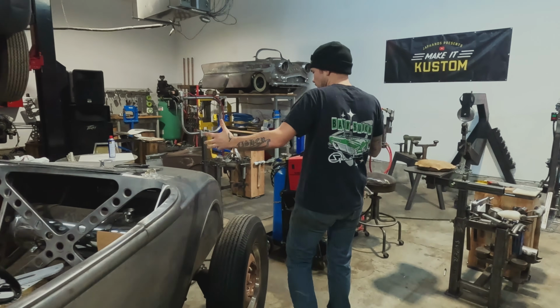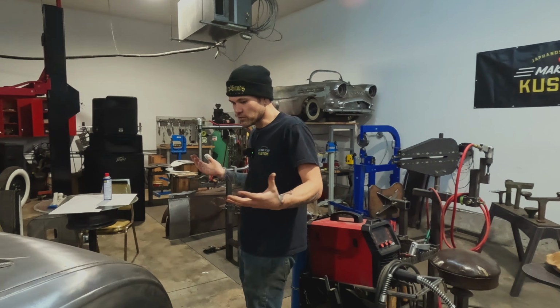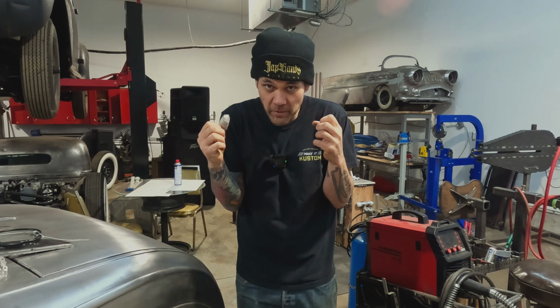Now, sheet metal is another thing that you would want to weld with TIG, typically if you're gonna hammer it, right? If we're gonna weld and then shrink, because if you watch the channel, when you weld anything, you're shrinking it. The heat expands, but it pushes the warm material into the cold material, and when it cools off, it actually ends up tightening back up and shrinking. So hammering your welds after you've finished welding will stretch them back out, creating a nice even panel again.